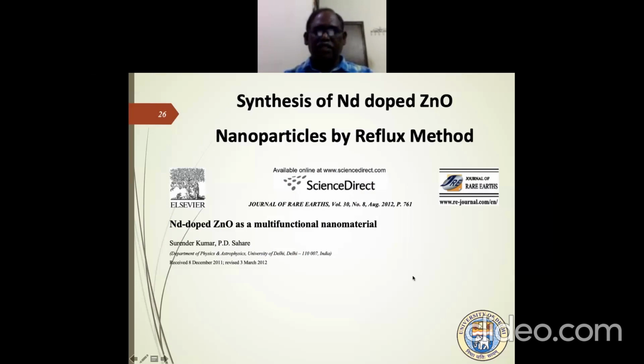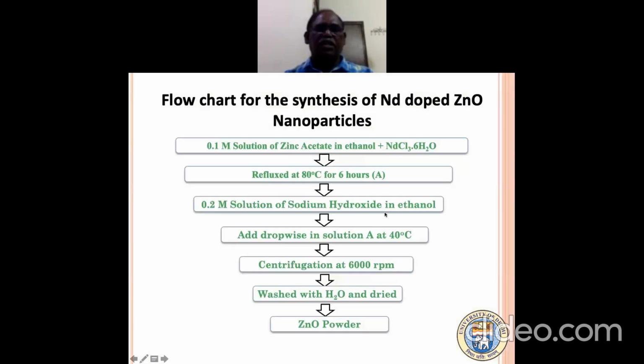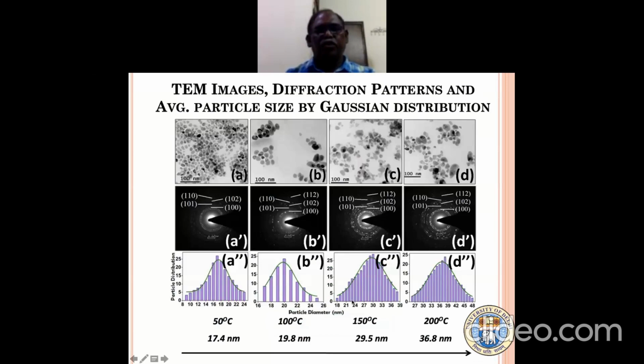This flow chart shows that we had taken zinc acetate with the neodymium chloride, which is soluble in water. We refluxed at 80 degrees for 6 hours, then reacted with sodium hydroxide in ethanol, added dropwise, and we found a milky color change. Then by centrifugation you can take it out, dry it, and use it. Here we found that by changing the temperature of the solution itself, you can change the particle size also.